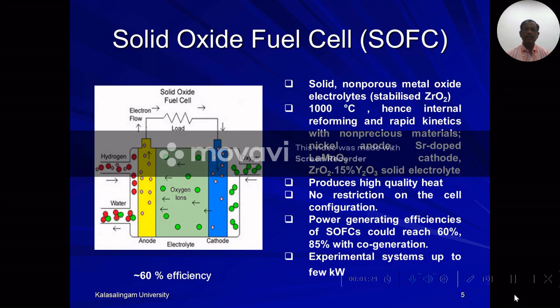My focus of the research is SOFC. SOFC has a YSZ-stabilized zirconia electrolyte, which can work at 1000 degrees centigrade, produces high quality heat, and has no restriction on the cell configuration. Power generation efficiencies could reach 60%, 85% with cogeneration. Research systems up to a few kilowatts can be generated.